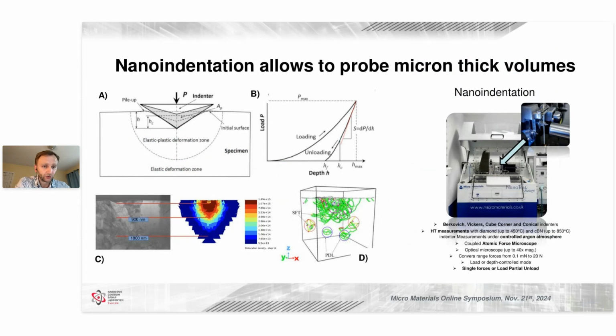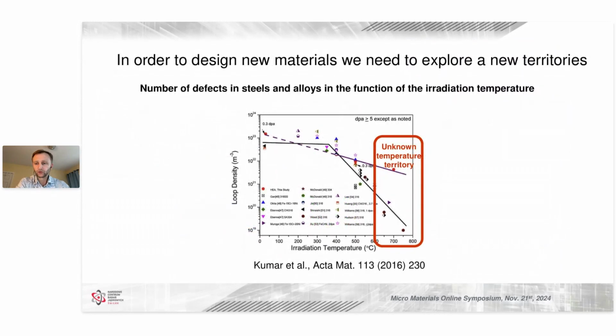At NCBJ, we are using a high temperature system, which allows us to heat up the samples up to roughly 800 degrees. It's a purge system, and today I will present a few results from these measurements. Another motivation for studies at high temperature is that there are very few data on how materials behave at temperatures exceeding 550 degrees. Therefore, my group and I position our research on testing in situ at high temperatures, just to understand the behavior of the material in the operating conditions of the given material.